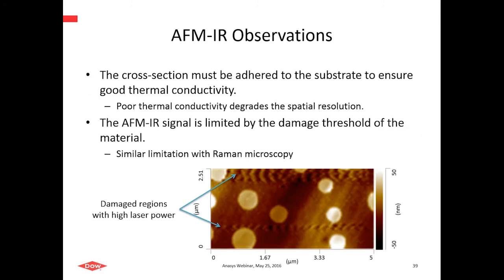So before I wrap up, I just wanted to talk for a second about some of the things that are important in experimental setup for AFM-IR. Since we're relying on this photothermal effect, the photothermal expansion, it's important that we have good thermal contact with the section that we cut to the substrate that it sits on. And that's easily achieved in the system setup with a beautiful, integrated optical top-down microscope and with low and high variable magnification, so you can find those regions of a section where it's well attached. Ensuring that gives us ultimate spatial resolution.